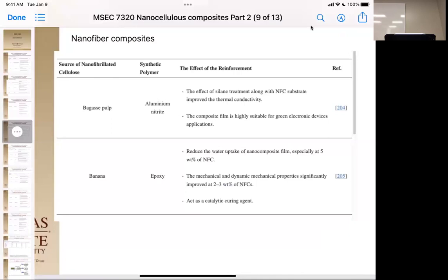If you think about it, there's a lot of surface energy on these things, a lot of hydroxyls. Normally, you would use an amine curing agent for an epoxy system because it's more nucleophilic. There's lots of hydroxyls here, and I'm sure that it's chemically bonded to the epoxy matrix as well. That's causing cross-linking. In this case, the hydroxyls on the surface of the nanocrystals can react with the epoxy. They do react slower than the amine, but they can. So I think it is actually chemically bound to the system, but also kicking off the reaction.